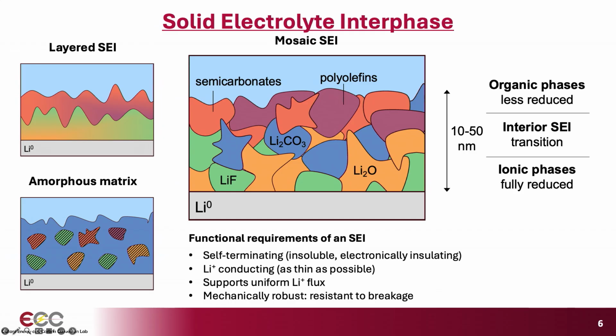So we know that closest to the lithium SEI interface, where we have the most reducing environment right next to lithium, you tend to find the most ionic, highly reduced phases, and that tends to be lithium fluoride and lithium oxide because most of our electrolytes rely on fluorine or oxygen, okay? Out here, closer to the electrolyte side, we tend to see less reduced, more organic phases derived from the solvent.